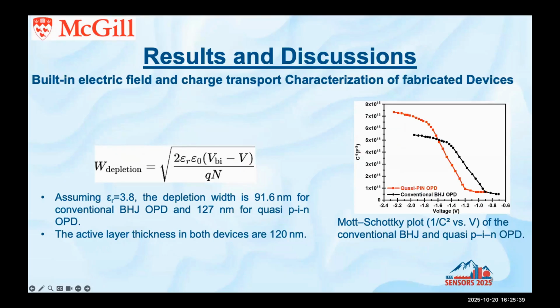And the most important thing, I can say, is that the active layer thickness in the devices was 120 nanometers. When we use the Mott-Schottky plot, based on this formula, we understood that the depletion width for the conventional device was 91.6 nanometers, and it was 127 for the new design device. And since this value is higher than the active layer thickness, we can say that our active layer is completely depleted in this new design.